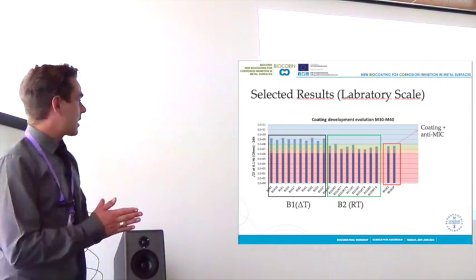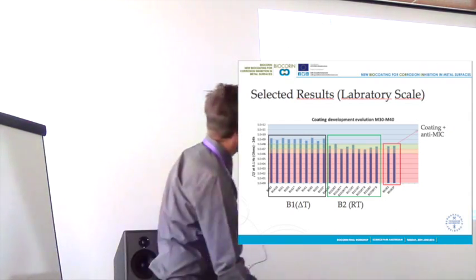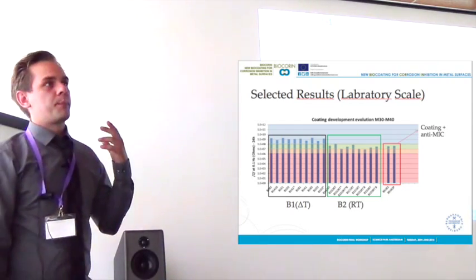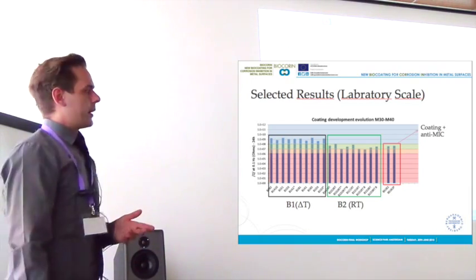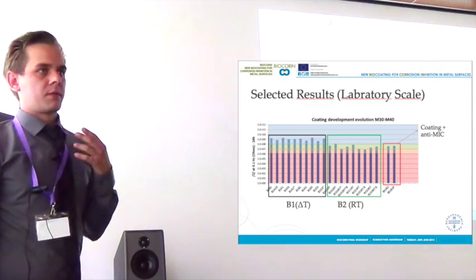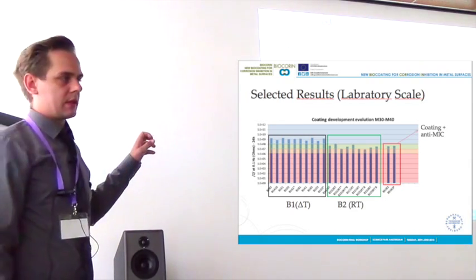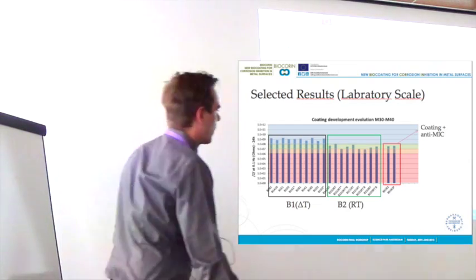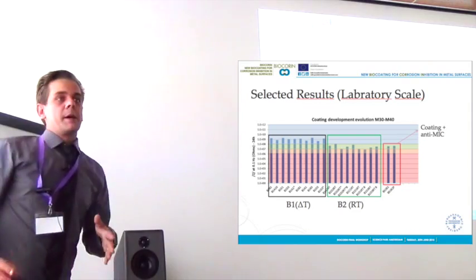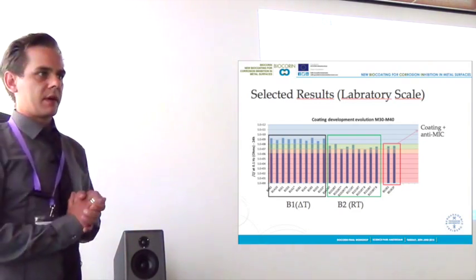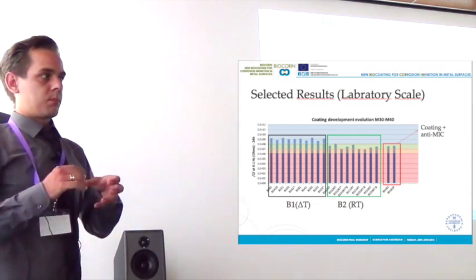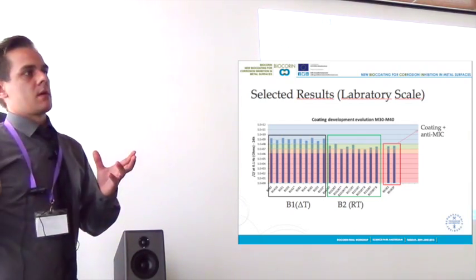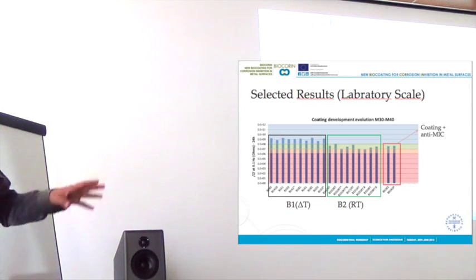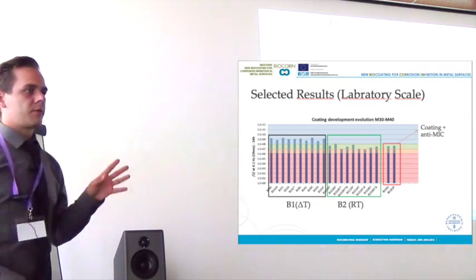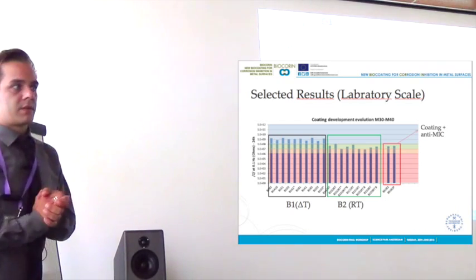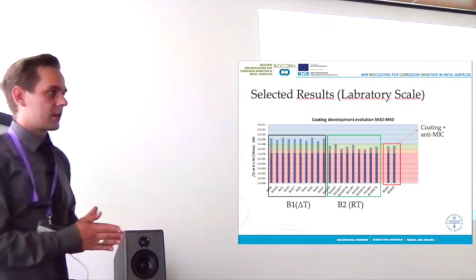These are some results that we have selected. B1 shows the best corrosion properties, and that can be explained because applying a higher temperature than 80 degrees leads to very fast evaporation of everything volatile in the mixture, and that leads to a very dense material. When using room temperature curing materials, you do the cross-linking, and during the cross-linking process the material starts to shrink, and this produces a pressure inside of the coating, and that leads to evaporation of the solvents in the coating. And if you don't use the right amount of catalyst or metal alkoxides, the shrinkage is too high, and you get a little difference in the coating behavior.